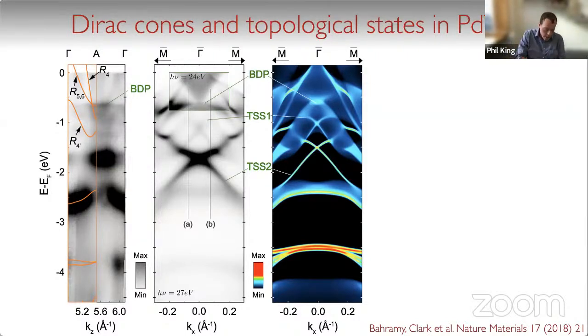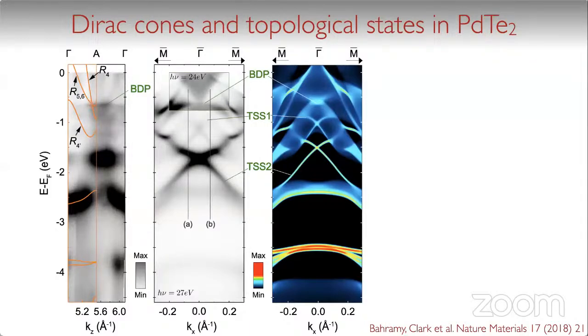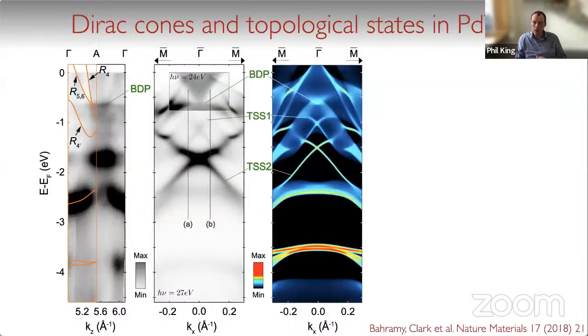So this one here is protected against spin orbit coupling by the C3V symmetry that you have in the system. So we think this one here is truly a Dirac point, a bulk Dirac point, whereas the crossing that would have happened down here is lifted by spin orbit coupling, which gives them the inverted gap down here. So you get both a protected and an unprotected crossing against spin orbit coupling.